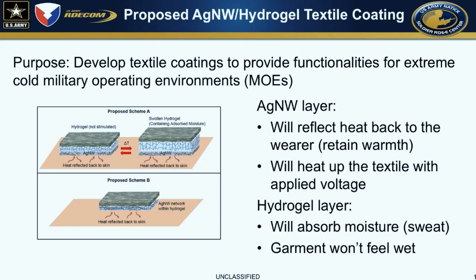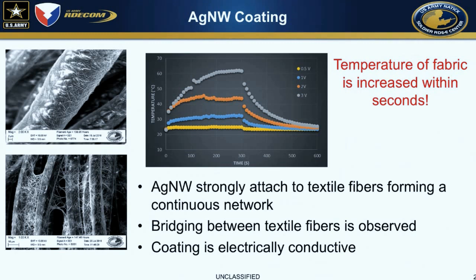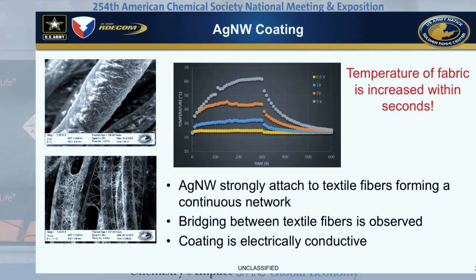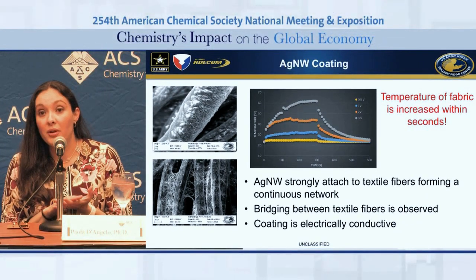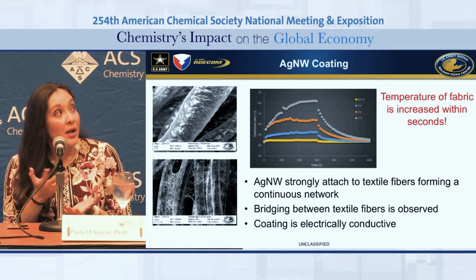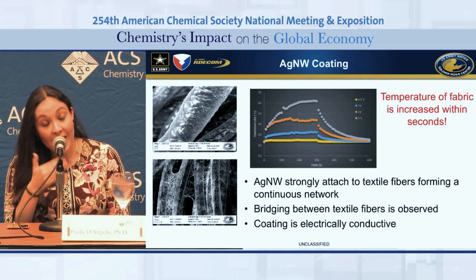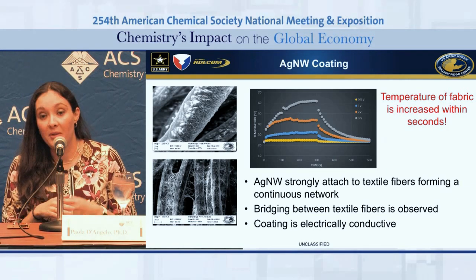So this work was inspired by Professor Cui's work from Stanford University. He basically developed this silver nanowire synthesis, and he coated it on fabric, and he found out that the fabric formed a continuous electrically conductive network. So inspired by his work, we are tweaking things a little bit to optimize this coating and couple it with the hydrogel layer. So I don't know if you can see the pictures from the slides, but when we coat the nanowires onto the fabric, the nanowires nicely wrap around the fibers, and bridge between the fibers, forming this continuous